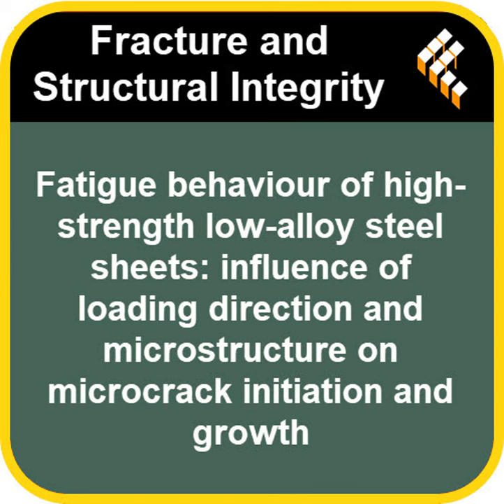For instance, in TD, the N prime value was low, like 0.076 at low plastic strains, but jumped way up to 0.35 at higher strains. So it's like the material's ability to toughen itself up changes depending on how hard you're pushing it. Exactly. Its hardening capability isn't constant. It shifts gears, you could say, depending on the deformation level. And they could actually measure this change afterwards, right?